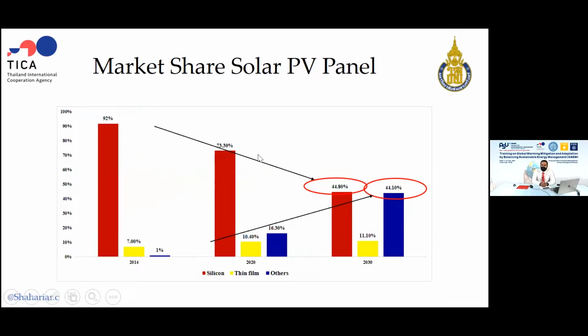So this is the market share of solar energy. We can see that in 2014, the market share was 92% silicon-based solar cells, and thin film based, like CdTe I mentioned earlier, was only 7%. And other solar cells like dye-sensitized solar cells, perovskite is still not commercially available, so it was only 1%. And researchers also predicted that silicon would reach 73.30% by the end of 2020. It's already gone, and thin film will achieve 10.40%, already achieved it, and other third generation solar cells 16.30%.